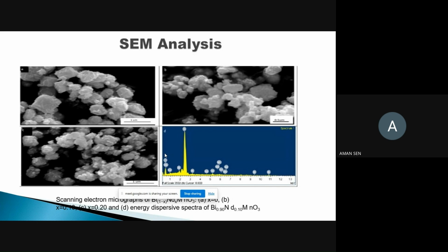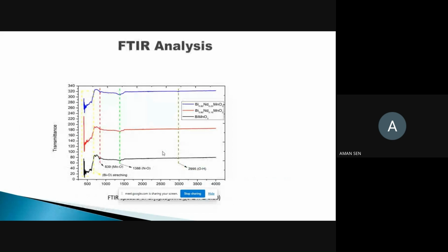This is because when we add Nd2O3 to our samples, it restricts the growth of the grains, forming more and smaller grains. With the substitution, the average grain size decreases because it provides more nucleating sites for the chemical reaction, promoting a larger number of grains.